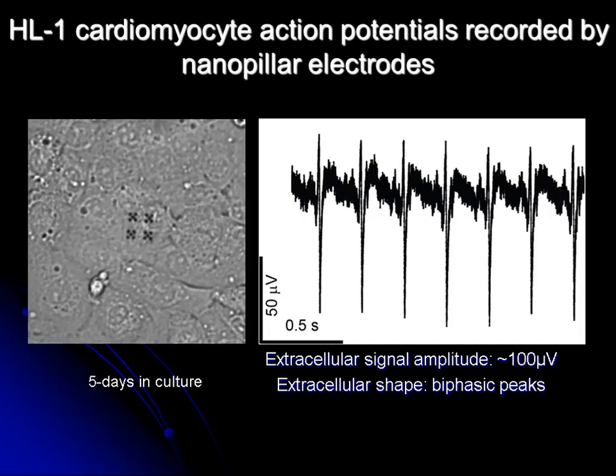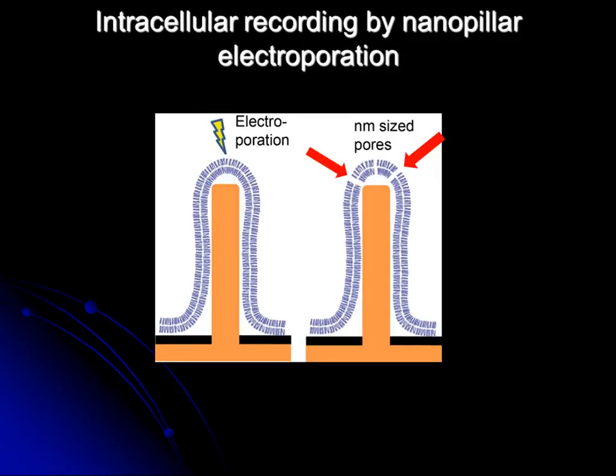And so when we first got this data, it was very exciting and also very disappointing. Very exciting in that we can actually record action potentials using the nanoelectrode, despite that it's very small. Very disappointing is that if you look at the shape of the action potentials, it's extracellular instead of intracellular. The peak is biphasic, going up and going down, and it's very small amplitude, about 100 microvolts. And so we spent quite a tremendous amount of effort.